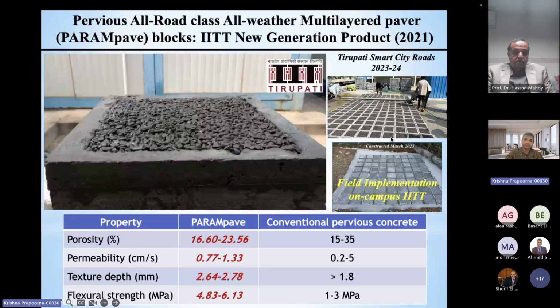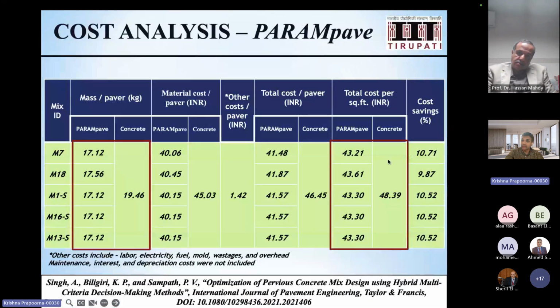So what we did recently, we constructed 850 meter of smart city roads with our blocks, as you see here. And we also calculated the cost savings coming up with our paver block, about 10% cost savings per block. You save about 5 units. I'm putting it in Indian rupees, but you can calculate that in dollars or in your currency. It's not very far. It's about 10% cost savings. And also it's lighter. It's about 2 kilograms lighter than the conventional concrete block.